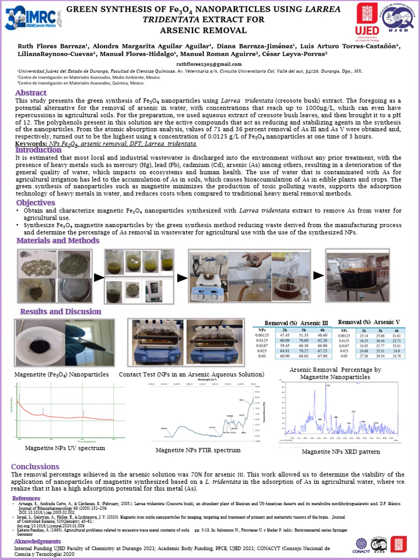In the table, we can see that for arsenic 5, the optimal time was also 3 hours and the same concentration of 0.0125 grams per liter of magnetite nanoparticles, obtaining a removal of 36%, with arsenic 5 being the most difficult to attract by nanoparticles.